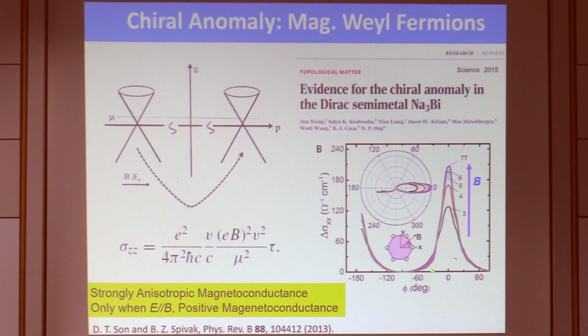And this has already been seen in various Dirac semimetals and Weyl semimetals. This is an example for sodium-3 bismuth. When you apply a field along the electric field, indeed, it shows a large enhancement of the magnetoconductance. And when you tilt a little bit, this drops quite dramatically because this condition no longer holds.